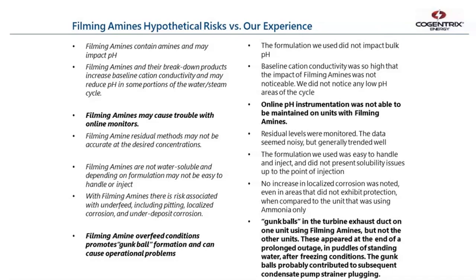There's a hypothetical risk that you could have gunk formation with the filming amines if you overfeed it. Most of the time we did not see any gunk formation, but we did in one instance, which I'll talk about more later. We had gunk balls in the turbine exhaust duct, and these actually appeared in the middle of an outage. I inspected that ACC duct with 3 different groups of people. The first time we inspected it, we didn't see any gunk balls, and the second time we didn't see any gunk balls, and the third time the gunk balls just appeared, right after a freeze. So something came out of solution, and I think it was temperature based. The puddles of water there had stuff in it, and it just came out.